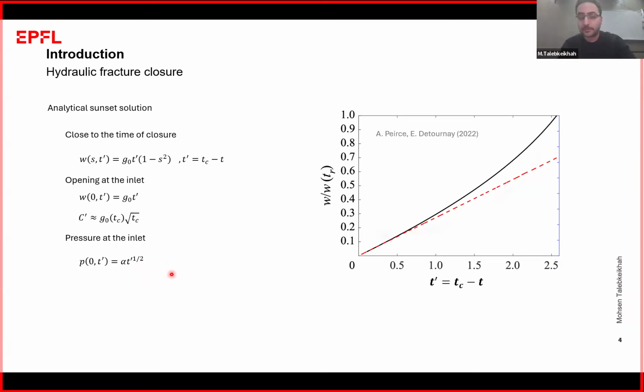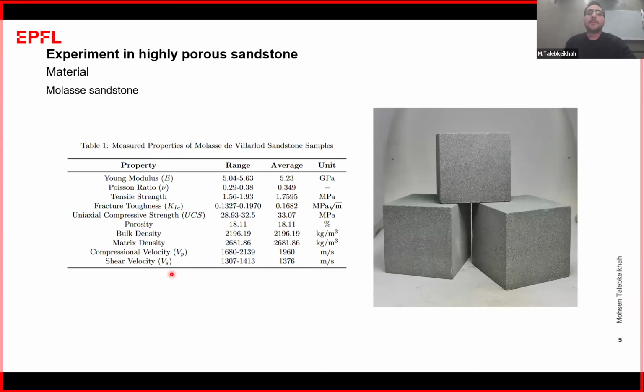To check the validity of the sunset solution, we need to design an experiment. To design that experiment, we selected Molasse sandstone from a quarry in Switzerland, which is highly porous. The porosity is about 20%, and it's a kind of weak sandstone, because the tensile strength is maximum 2 MPa, and the Young's modulus is around 5 gigapascal. The reason that we selected such a sandstone for doing hydraulic fracturing is just to speed up the process of the closure. We really want to have multiple cycles of injection and closure, and we want to practically do it in our lab. So we need to have a high leak-off sample.